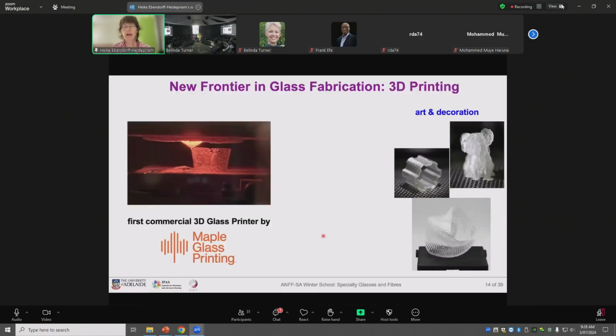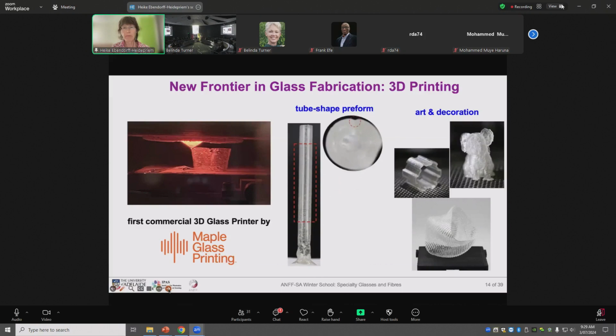Another extrusion-based technique is 3D glass printing. And this really has come up in the last 4 to 5 years. We have a commercial 3D glass printer from Maple Glass Printing, a startup company in Melbourne. And you see here the glass is coming out of the hot nozzle, a thin glass strand, and then layer by layer the glass piece is built. We started to investigate the 3D glass printing from a glass art point of view, and so we made these various glass art pieces, but also then we looked into making a tube-shaped preform, which then we have also drawn to fiber.